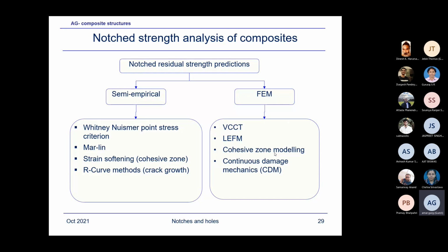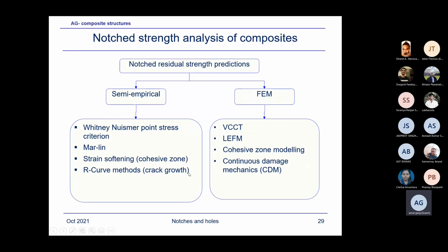Notch strength analysis of composites. So, notch residual strength predictions: semi-empirical and FEM. In semi-empirical, we are going to discuss now the Whitney-Nuismer point stress criteria, the Mar-Lin approach. Another approach is strain softening, which I'll not be discussing now because it's a bit complex and involved. I've deleted this. In fact, I had developed this approach for other predictions while I was at Boeing. R-curve methods, crack growth analysis, this also I'll not be presenting. I think the most important are these two approaches, and this is what I'll be discussing so that you get a feel how to determine the residual strengths.